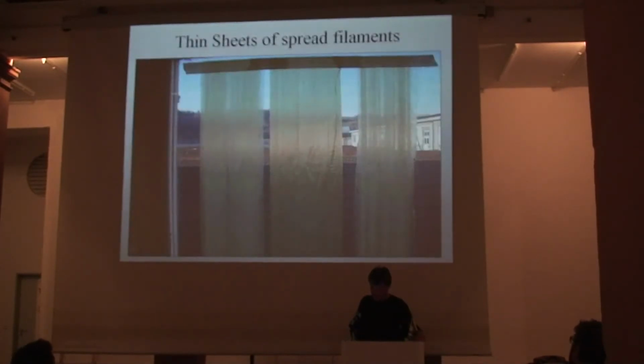So those individual filaments here are taken out of the bundle and laid side by side in these super thin tapes. So one of those tapes is equivalent to maybe 12 of those yarns, and all the filaments are laid side by side embedded in resin. And so in that configuration, you've got the same material that your competitors are using, but you've improved the way the material is configured by breaking it down and reassembling it in the manner you desire, and it's 15% better material properties. So the implication of that is the sail can be 15% lighter or 15% less stretchy.